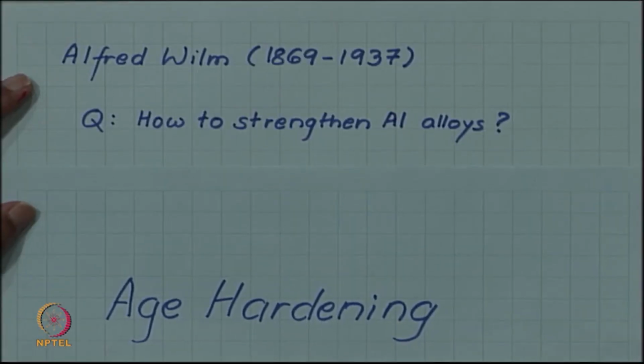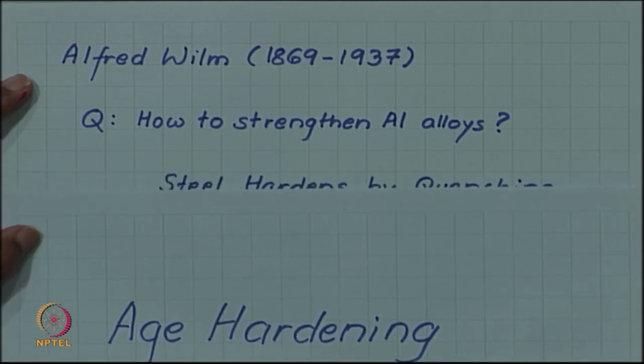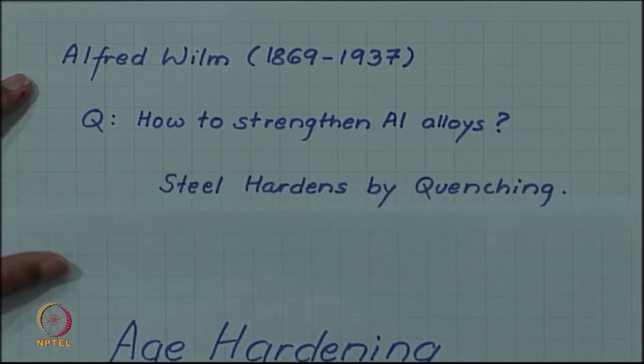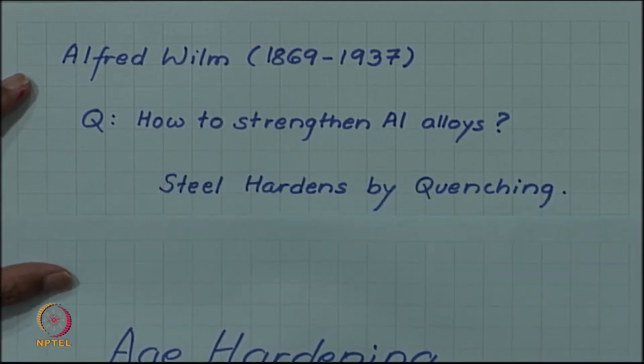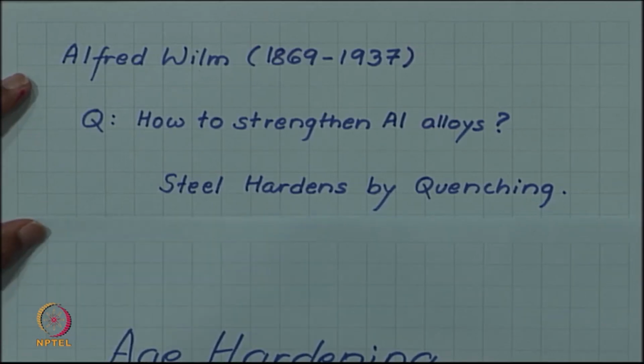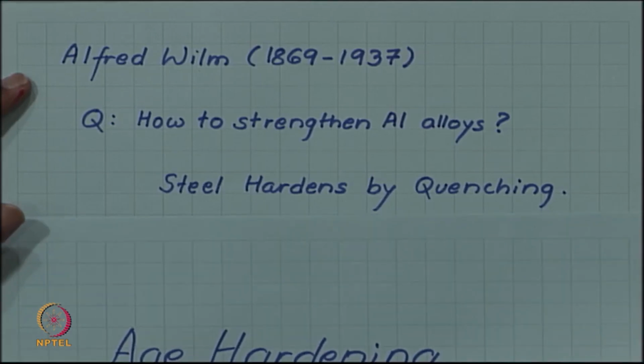So, then he had the background from steel, that steel hardens by quenching. So, we have seen that steel, if taken to the austenite phase field and then quenched rapidly enough to miss the nose of the TTT curve, it hardens because it forms a very hard and brittle martensite. So, steel hardens by quenching.